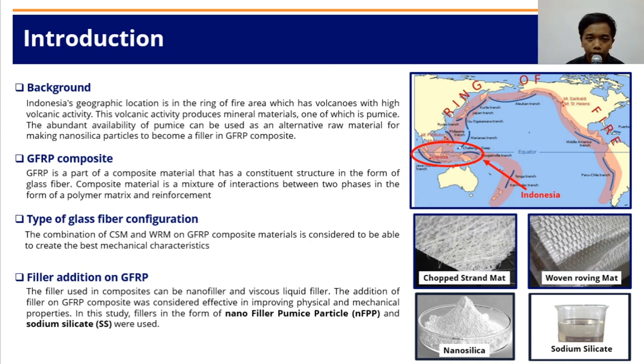In composite material structure, two types of glass fiber configuration are generally used. The first is chopped strand mat and the second is woven roving mat. Several studies have proven that a composite with unsaturated polyester resin reinforced with woven roving mat glass fiber shows a good strength, whereas the composite with a chopped strand mat reinforcement has a good flexural strength, so the combination of chopped strand mat and woven roving mat glass fiber on GFRP composite material is considered to be able to create the best mechanical characteristic.